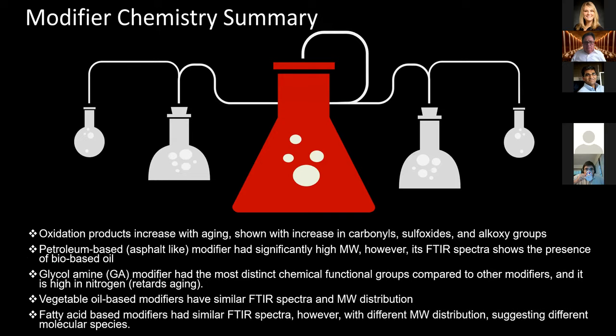Oxidation products increase with aging. That was shown with those increases in carbonyl, sulfoxides, and alkoxy groups previously. The petroleum-based asphalt-like modifier had a significantly higher molecular weight. However, its FTIR spectra shows the presence of a bio-based component as well. The glycolamine modifier had the most distinct chemical functional groups compared to the other modifiers, and it is high in nitrogen, which is known to retard aging.